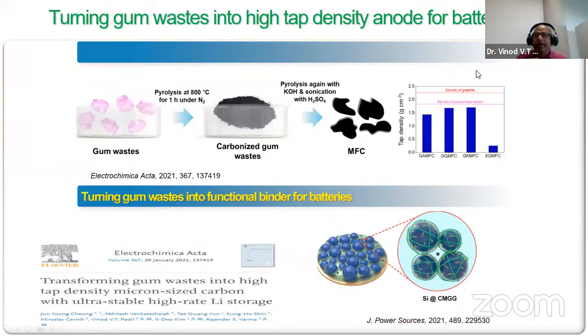So this again we converted into electrode material and used for high rate of lithium storage. This work has been published in the Electrochimica Acta recently. So how we can transform the gum waste into high tap density micron size carbon with ultra stable, high rate lithium storage.